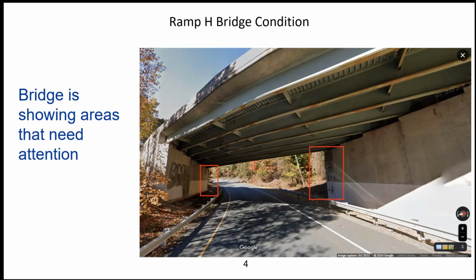And of course, if we repair those abutments, being vertical walls, the repair usually either involves adding concrete cast in place, which usually means a minimum of 4 to 6 inches, which is significant weight and significant effort. And of course, it adds dead load to the substructure and the foundation. The other option is spray applied or shotcreting, where you can apply a thin layer to provide the protection. And in this case, UHPC will provide the protection and restore the durability of the abutment. Next slide, please.